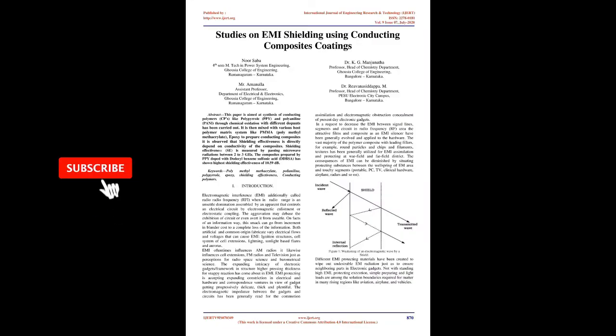Studies on EMI shielding using conducting composites coatings. Abstract: this paper is aimed at synthesis of conducting polymers, CPs, like polypyrrole, PPY, and polyaniline, PANI, through chemical oxidation with different dopants. It is then mixed with various host polymer matrix systems like PMMA, polymethyl methacrylate, and epoxy to prepare conducting composites.